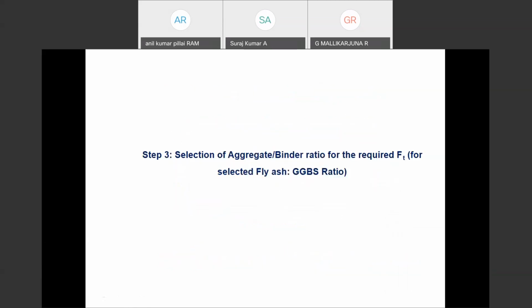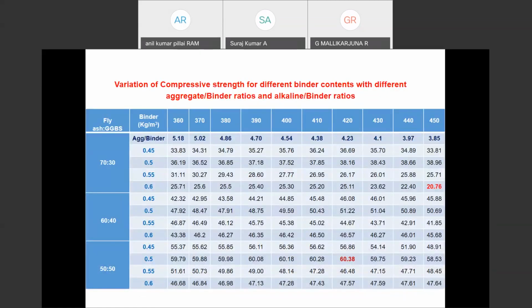And next, we had drawn charts for the selection of aggregate to binder ratio for required target strength for different fly ash and GGBS ratio mixes. Here we have taken mixes of 360, 420 and 450, so that we have drawn charts with the different alkaline to binder ratio. Here 70-30 indicates fly ash and GGBS, and the binder content we are going to take as 0.45, 0.5, 0.55 and 0.6. And the aggregate to binder ratio varies from 5.18 to 3.85 here. Whatever binder content you require, you can select your aggregate to binder ratio, alkaline to binder ratio 0.45, and based on your required strength you can select the different types of mixes.